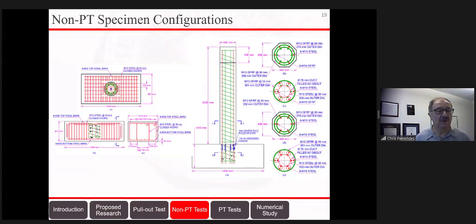So again, going back now to the non-post-tension tests, I'm showing again the cross-section of the column and the reminder that there was a little bit of debonding inside the footing, roughly 6 inches. But you can see here the 12 bars that are used. In this case, in the hybrid case, 6 are steel and 6 are fiberglass. And in the all steel case, all 12 bars are, of course, steel.